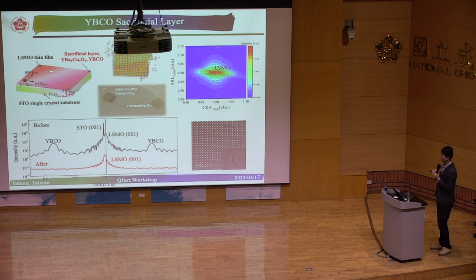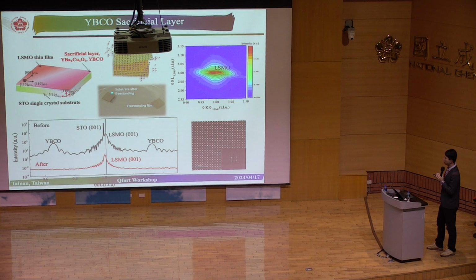Compared with LSMO, which is the previous sacrificial layer proposed in Berkeley's group, which usually can be easily etched. But this time, what we do is use YBCO as the sacrificial layer, and on top we grow LSMO. You dip them into the very light acid solution, and after probably 10 or 20 seconds, this is what you can see. The epitaxial single crystal substrate just drops at the bottom, and on the surface there is a floating freestanding thin film. This is exactly what we can do.